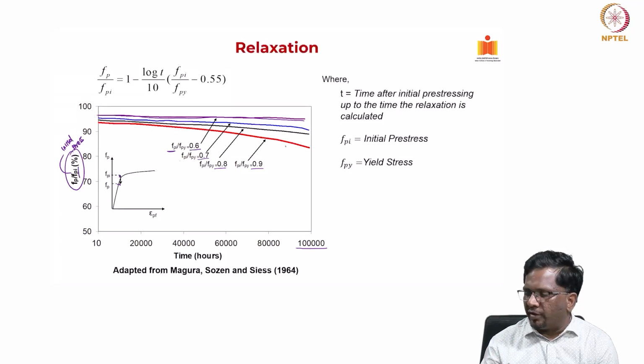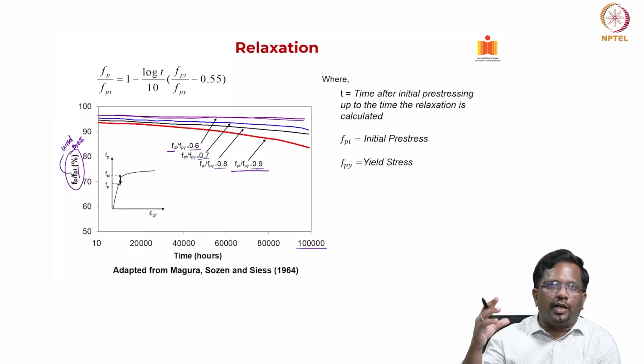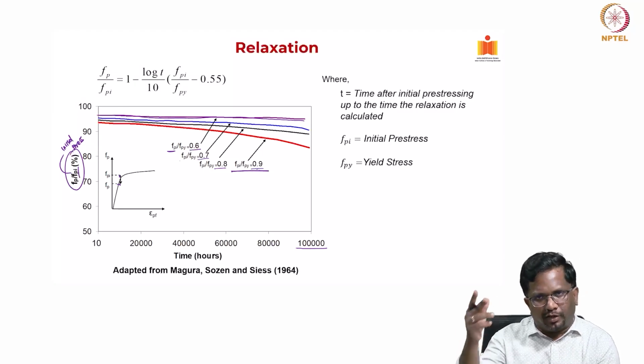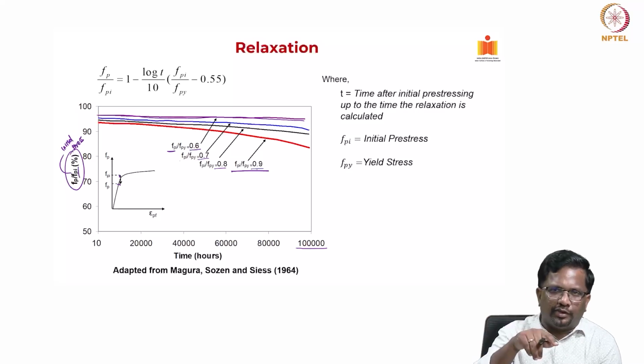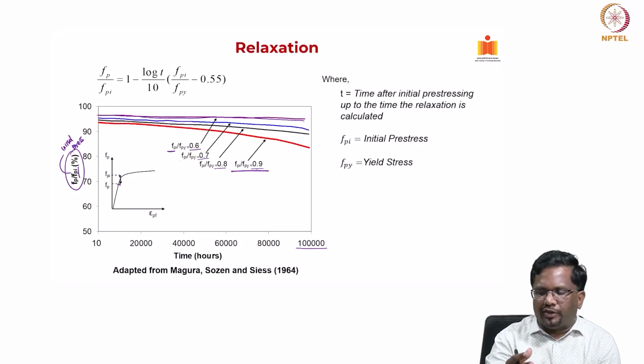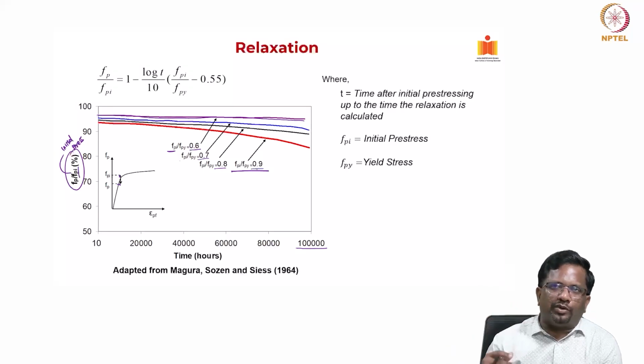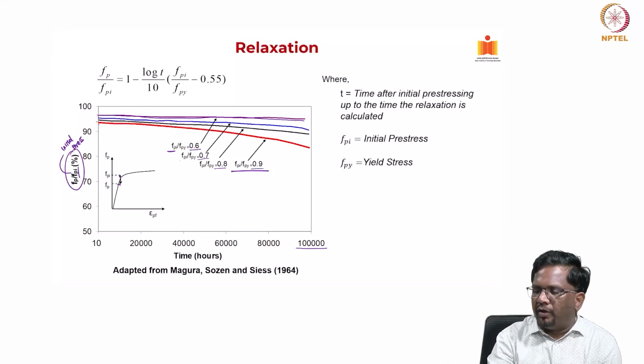Let us look at the red color curve. The red color curve is FPI by FPY equal to 0.9. That means the initial stress is 90% of the yield strength. How we calculate yield strength we have seen. Roughly we take that as FP 0.1 K, right. So, that worked out to be around 15 something that we saw in the previous slide, right. So, if I am applying stress very close to that of yield, you will find that the loss in pre-stress due to relaxation will be quite high.